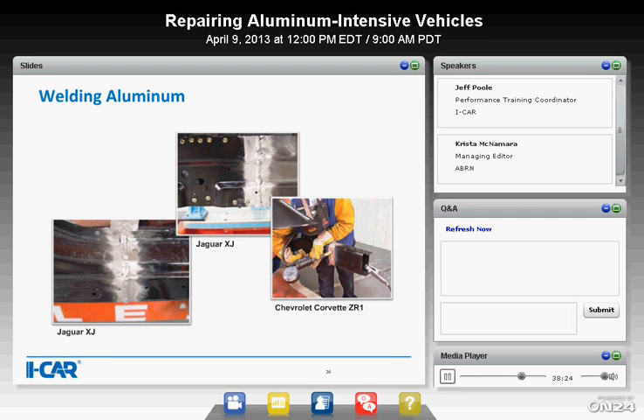The electrode wire selection is critical to achieve a strong weld. This electrode wire is going to mix in with the base metal alloys in the weld puddle, and then it reformulates. If we choose the wrong electrode wire, this can result in undesirable weld composition and a weak weld or a weld that cracks. In some cases, you may find you're joining two different alloys with yet a different electrode wire alloy as the prescribed repair for the vehicle. So again, we're not the chemist per se. We just want to make sure that we're looking at what the doctor ordered so far as the repair.